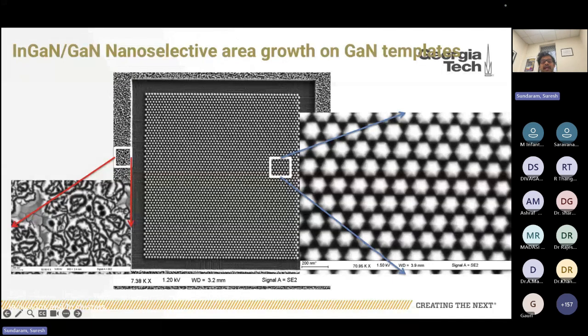On the edges, we have a 2D material which has a lot of defects. And on the patterned area, you can see hexagonal indium gallium nitride nanopyramids. You can see all the facets. It's perfectly crystalline without any visible defects in all these areas. So here we can avoid relaxation induced defects by using the nanoSAG process.